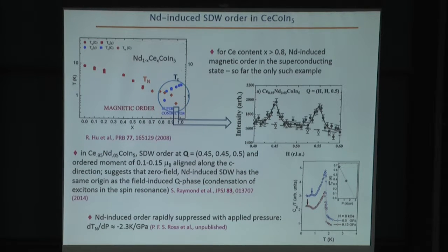Now, besides the magnetic field, replacing a small amount of the cerium by neodymium also induces magnetic order, and so far neodymium is the only substitution that shows magnetic order developing in the superconducting state, and that's reflected in this temperature-doping phase diagram, where we see, for example, at 5% neodymium, the superconducting transition temperature of pure cerium cobalt-5 is reduced a little bit, but there's a phase transition that develops inside the superconducting state that's been seen by specific heat. And neutron diffraction shows that this anomaly in specific heat below Tc is in fact spin density wave order. Here are the data. And lo and behold, the ordering wave vector here in this neodymium-induced spin density wave is (0.45, 0.45, 0.5). The ordered moment, again, is somewhere between 0.1 and 0.15 Bohr magnetons, and that ordered moment is along the z direction.